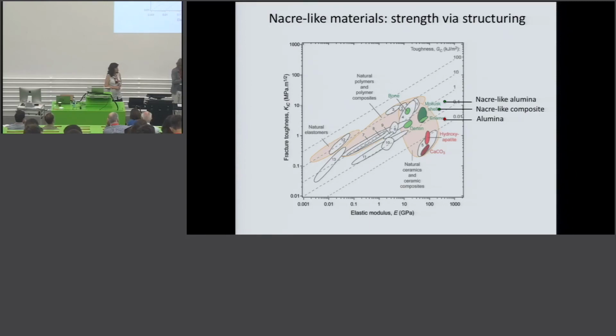So the key design principle here is to keep the volume fraction as high as possible. That's why it's 95%. And then tune how much these platelets are interconnected in order that you're just below this critical aspect ratio. Yeah. Thank you.